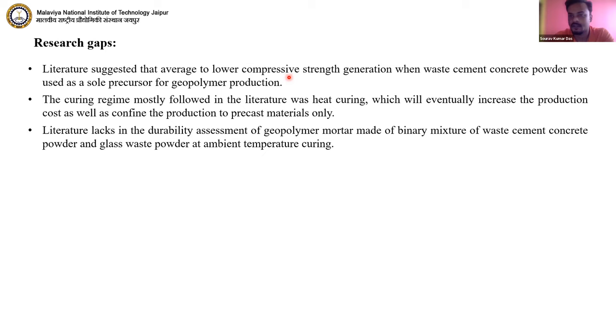And the curing design that I've already discussed is mostly heat curing. So in my research, I have maintained an ambient temperature curing throughout the process. So it was 30 degree centigrade. I maintained this temperature to see whether my mix can attain the strength or not within this temperature.